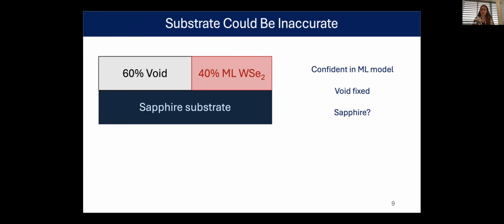I went back to how I was structuring my model. The way it was working in the software, which is CompleteEASE from the J.A. Woollam Company, we have a model for the sapphire substrate. And on top of that, we have this EMA, which is where I'm measuring that coverage. So for example, if there were 40% monolayer coverage, it would be only 40% of that model is where I'm plugging in what I have set for the monolayer. The other 60%, I'm saying there's nothing on the substrate, so that's void, which is fixed in the software. So that top layer, we feel pretty confident in.